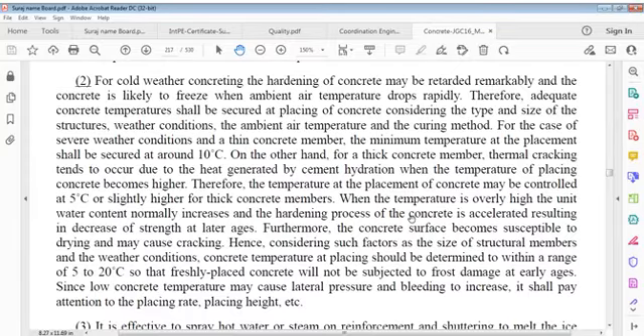On the other hand, for a thick concrete member, thermal cracking tends to occur due to heat generated by cement hydration when temperature of placing concrete becomes higher. Therefore, temperature at placement of concrete may be controlled at 5 degrees Celsius or slightly higher for thick concrete members. When temperature is overly high, unit water content normally increases and hardening process of concrete is accelerated, resulting in decrease of strength at later stage. Furthermore, concrete surface becomes susceptible to drying and may cause cracking.